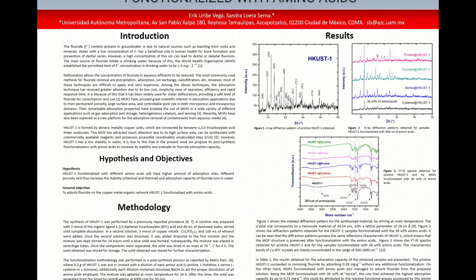Figure 2 shows the diffraction patterns obtained for the HKUST samples functionalized with the amino acids proline, tyrosine, cysteine, and serine with 36 weight percent. It can be seen that the diffraction patterns possess the same reflections characteristic of HKUST, which means that the MOF structure is preserved after the functionalization with the amino acids. The crystal size D of the functionalized MOF corresponds to nanometer scale materials between 29 and 33 nanometers. It was observed that D increased with the amount of the amino acids for most of the samples obtained, being the largest crystals those of the functionalized samples with 36 weight percent.